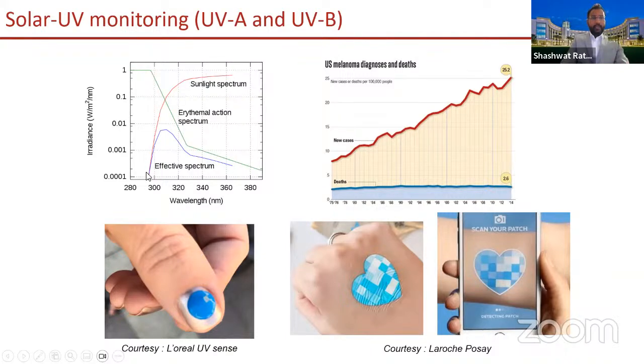For instance, if you look at the sunlight spectrum, as we discussed, it tails off and we don't see anything below 290 nanometers. But if you look at the skin sensitivity to these radiations, it goes up as the wavelength goes down, because as the wavelength goes down, the energy of these photons goes up. So each of these photons has a higher energy, and it interacts with our skin significantly as we go below 300 nanometers. This is why having the ozone layer above us is so critical for human existence. Because if we didn't have that, then everyone would have skin cancer to start with.